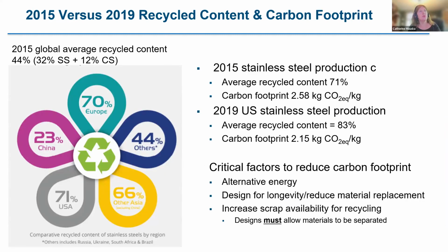I'm showing 2015 data, and you can see the average recycled content around the world. I've noted that globally the average was 44%, 32% stainless steel, 12% carbon steel. In the US, it was 71%. But we have new data from a 2019 study that will be published shortly. The average recycled content in the United States is now up to 83%. And as you can see, that substantially reduced the carbon footprint of the stainless steel.